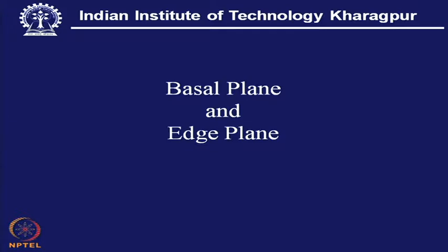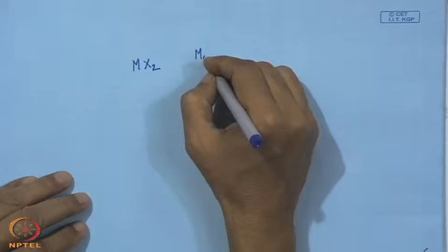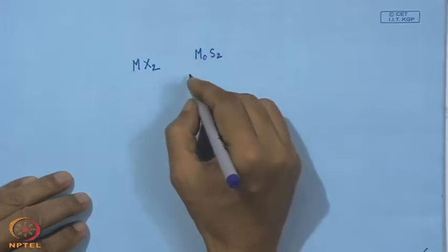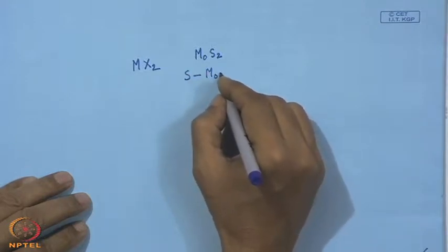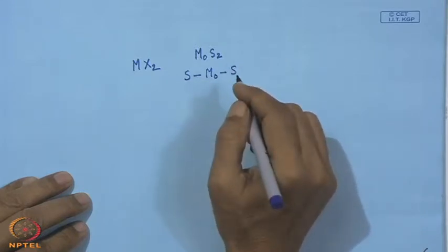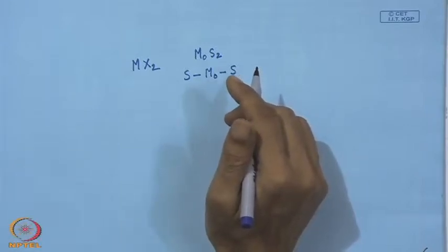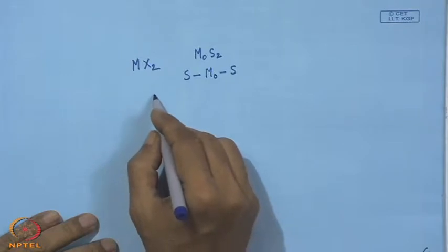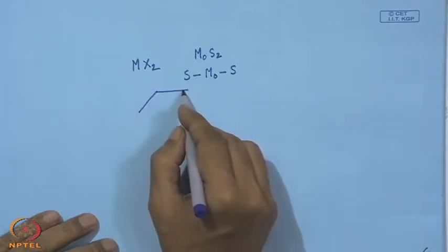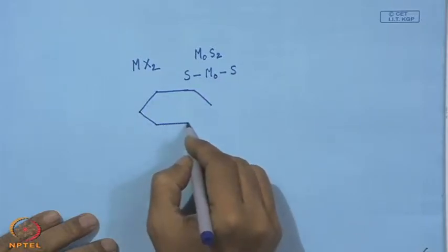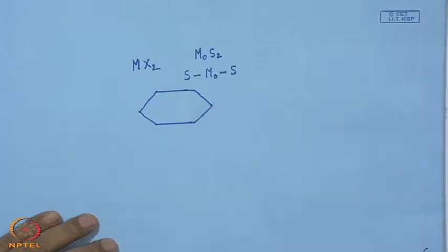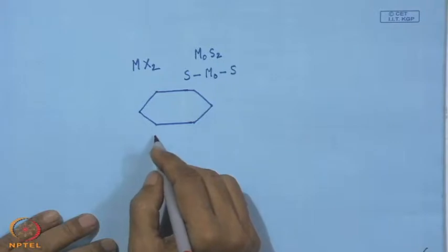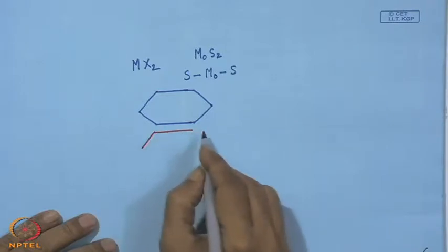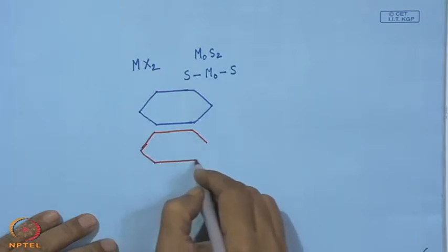Now, to look into this issue, what we can see is MoS2. That means it is as if it is S, Mo and S. So, when we like to see its structural formation, we can see that we have a hexagonal array of this sulfur and molybdenum. So, this is actually one plane containing the sulfur in a hexagonal arrangement, and adjacent to it, we have another plane, and this plane is the plane containing molybdenum. This is also in a hexagonal array.